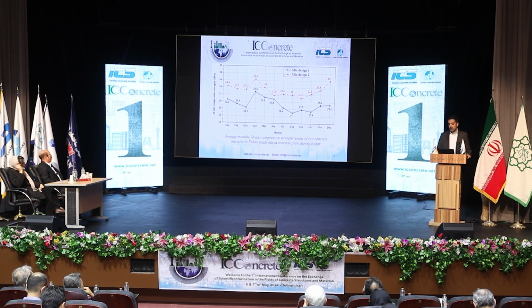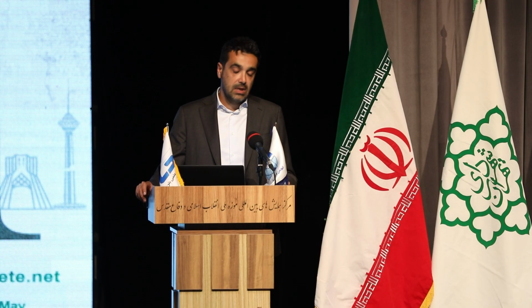These results show the obtained average compressive strength of 2 specific concrete mixtures during a year. As you can see, in the summer months, the average 28-day compressive strength is lower in comparison to other months, which shows that in summertime we should implement some measures to compensate for this reduction.